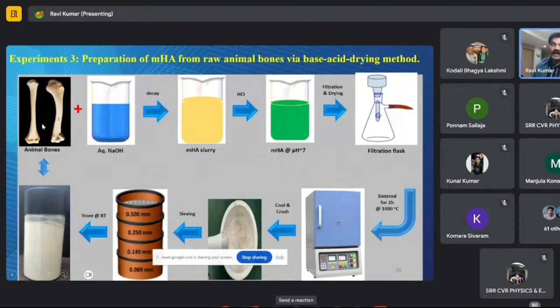So first you take the animal bone. After conversion, it is powder. This is a nano powder. Sometimes it is micro powder. So after treatment with NaOH for more than 20 days, it decayed due to the hydroxy groups, and it formed the slurry. That slurry is again treated with acid for neutralization, at pH 7. And later we filtered and dried. After drying, we sinter it for 2 hours at 1000 degrees Celsius, cool and crush it, and sieve it with different sieve sizes, and we get the final nano product. It is a nano and micro product mixing at room temperature.